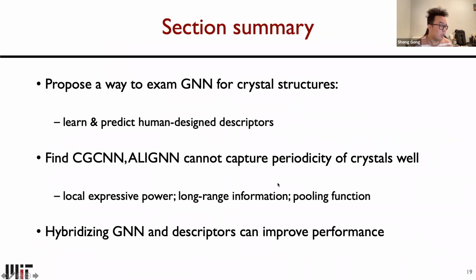Okay, in summary, here we propose a way to examine graph neural network for crystal structures, which is to learn and predict human designed descriptors. We found that CGCNN and ALIGNN, which are 2 classic GNN models for crystal structures, cannot capture periodicity of crystals well because of the limited local expressive power, the long-range information, and the choice of average pooling as the pooling function. And we propose to hybridize GNN and the descriptors to improve the performance of property prediction.